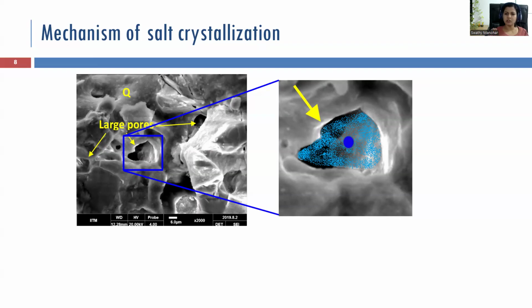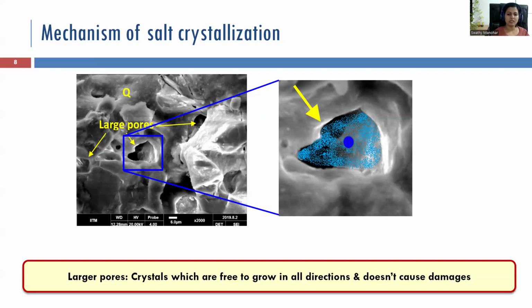The crystal is free to grow in all directions. There is no restraint or constraint for the growth, so it will not cause any pressure on the pore walls. It's free, stable, settled there, growing. So in larger pores, crystals are free to grow in all directions, so it doesn't cause damage.